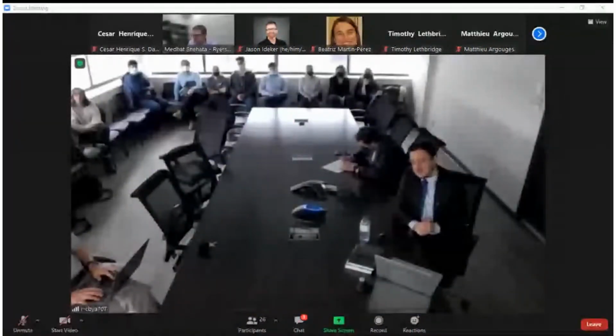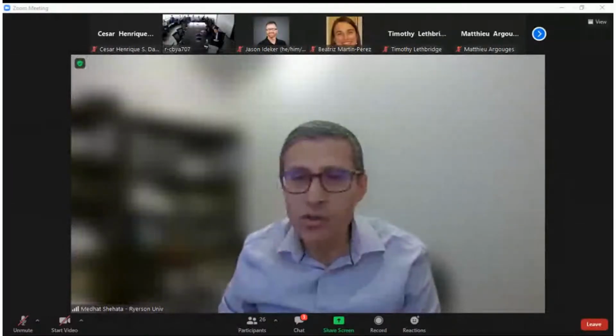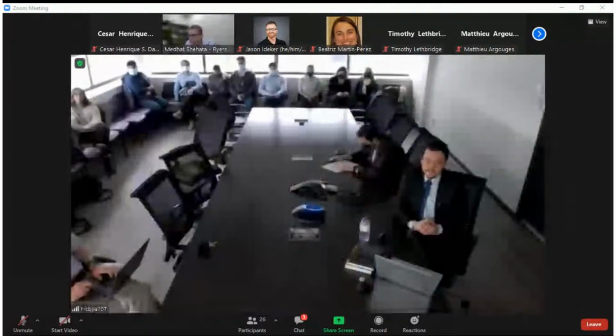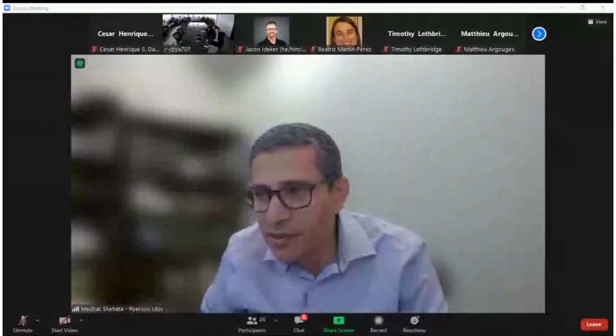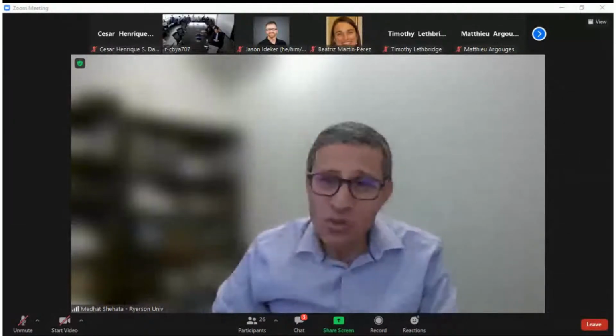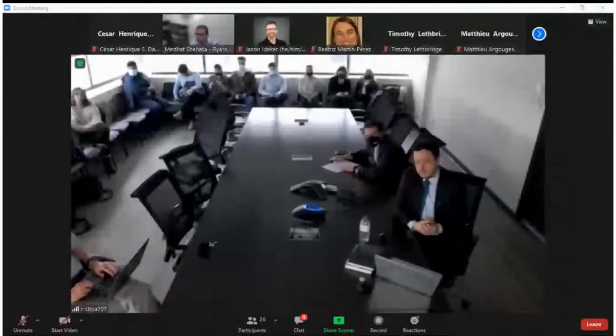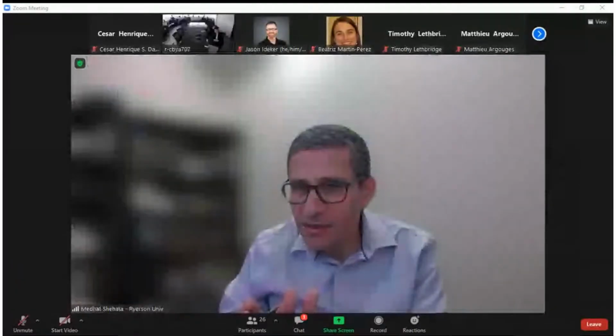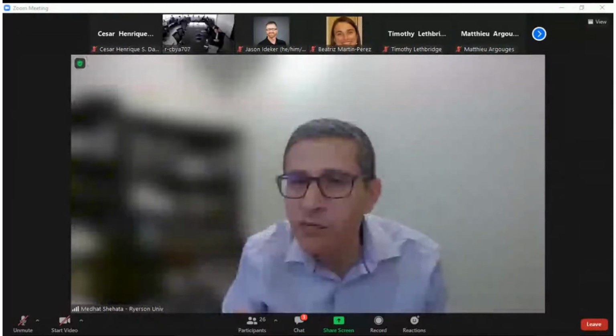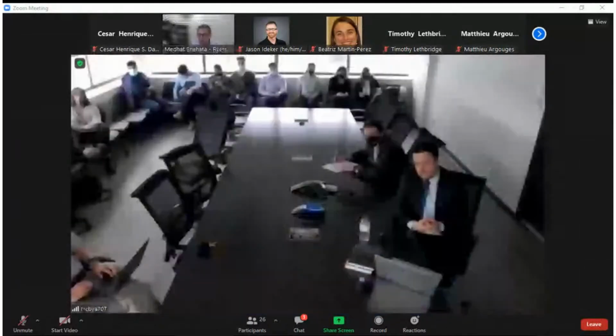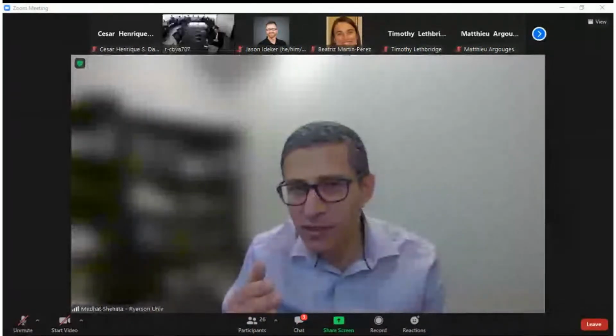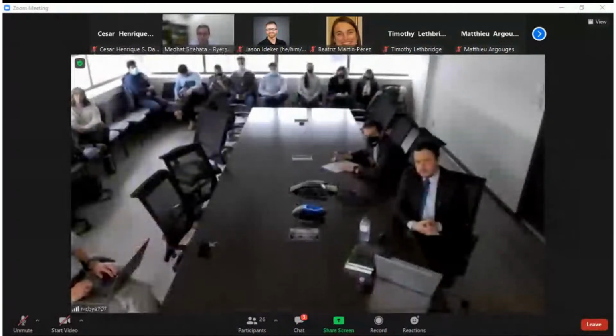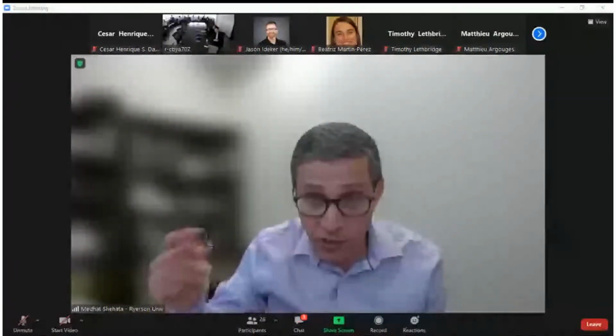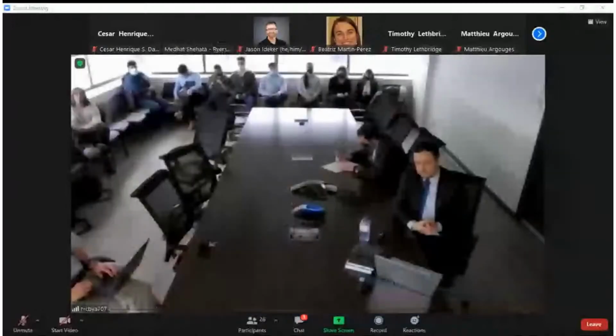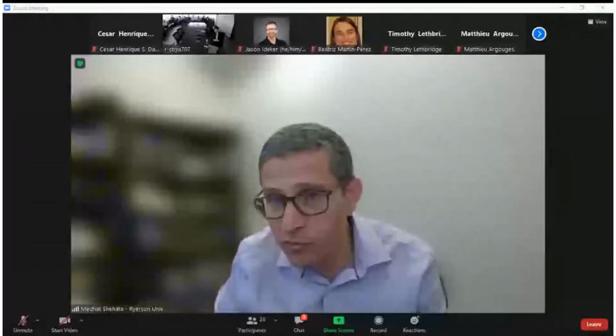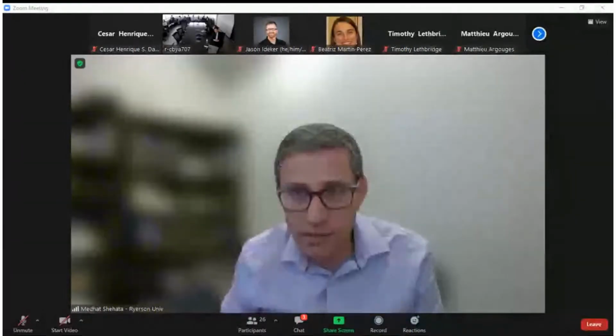You're right. And then let me ask you another question about the oxide. When we talk about alumina, silica, the calcium oxide in general, I was in the same boat maybe 25 years ago, and we developed relationships between the oxide and the expansion. But we have to be very careful about the form of the oxide. For example, if that silica is in the form of quartz, it's crystalline, it doesn't contribute to the reaction. If you have quartz in the fly ash, and it's more important for alumina, because most of the aluminum in fly ash is actually in the form of mullite, crystalline again, so it doesn't really contribute.